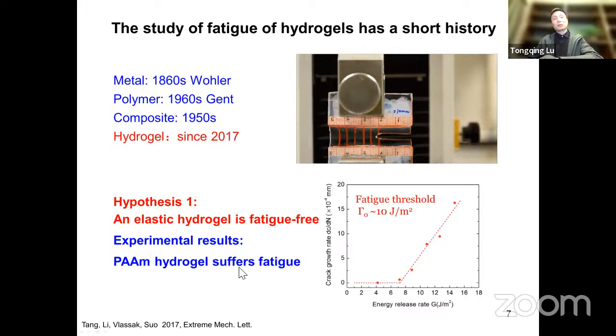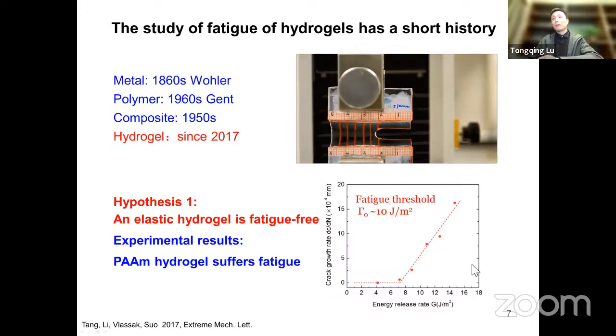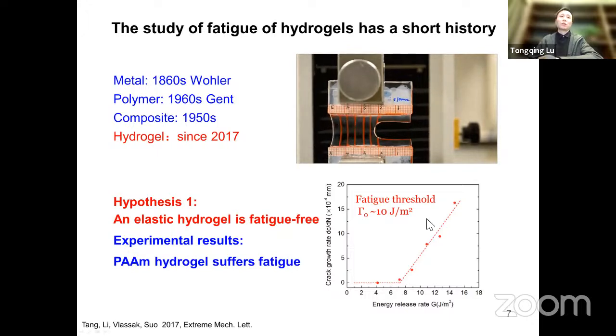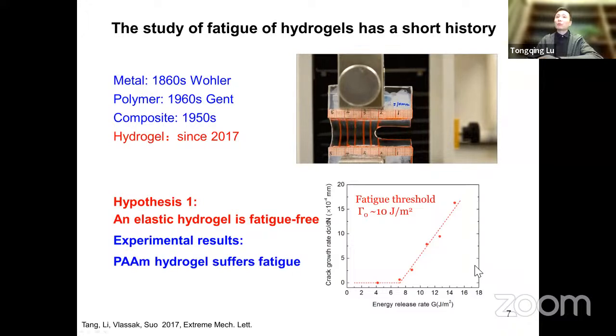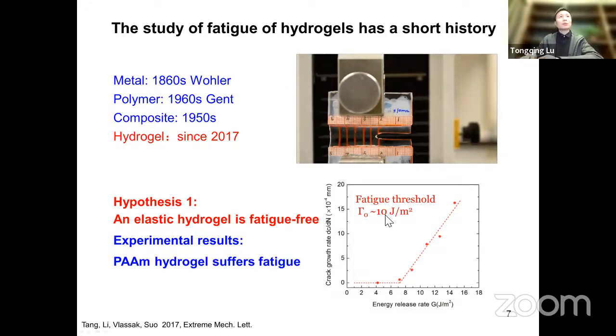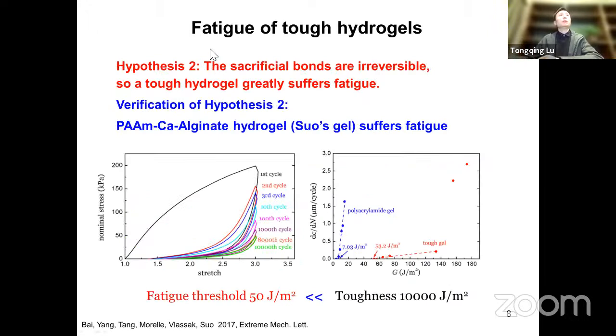When we see a material suffers fatigue, we mean the toughness is much larger than the threshold. It means if you stretch it, the toughness is about 100 joule per meter squared. But if you load it cyclically, the fatigue threshold is only about 10. Okay. So now we proceed to study the fatigue of tough hydrogels.